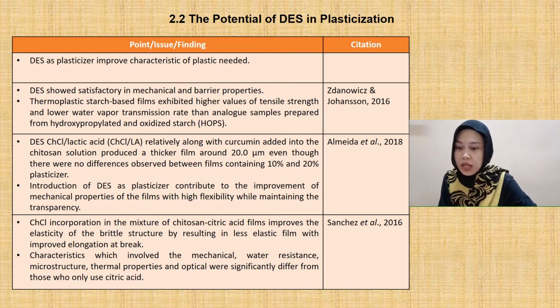DES ChCl-lactic acid used relatively along with curcumin added into the chitosan solution produced a thicker film, around 20.0 micrometer. Lastly, Sanchez et al. 2016 mentioned that characteristics which involve the mechanical, water-resistant, microstructure, thermal properties, and optical will significantly differ from those which only use citric acid.